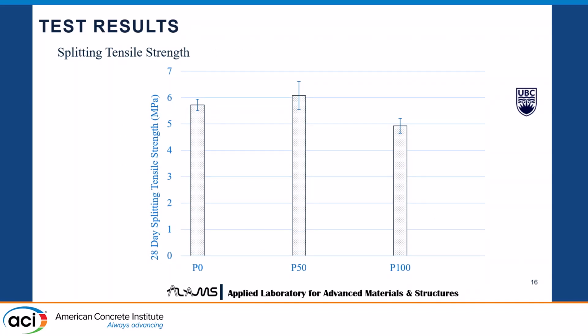Then we can see the splitting tensile strength. So the control one gave us around 6 MPa, 5.7 to be exact. But with 50% poraver and 50% sand, it had the highest strength. It's more than 6 MPa. And with P100, we are getting 4.9 MPa, which is not bad. So P50 had higher strength because it had two types of sands. So the one with poraver, which are fine sands, and the silica sand, which is coarse. So I guess it had a good aggregate interlocking. That's why it had a better strength than the other two.